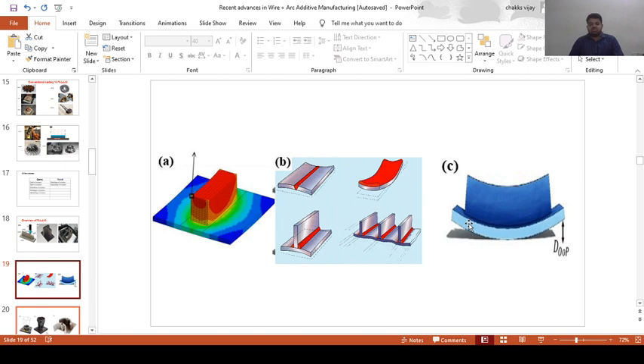The plate will initially be at room temperature, 32 degrees C, and suddenly it is exposed to a very high heat like 1600 or 2000 degrees C. Obviously this base plate could not withstand that high thermal shock, which leads to residual stress complications and plate distortion. Once the plate is distorted, all the coordinates, x and y axis, that we fixed prior to deposition get altered, so it would end up as a failed component, which we never needed.